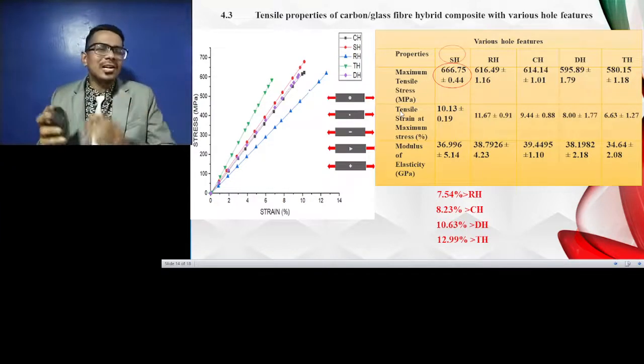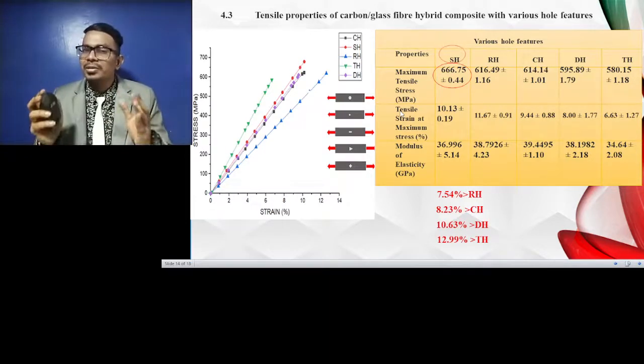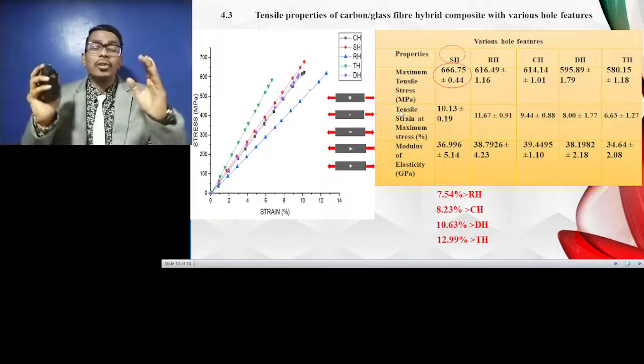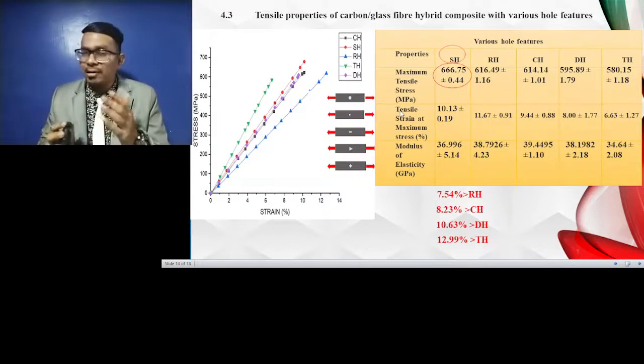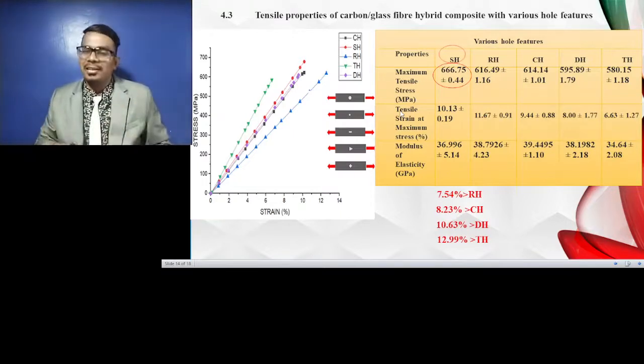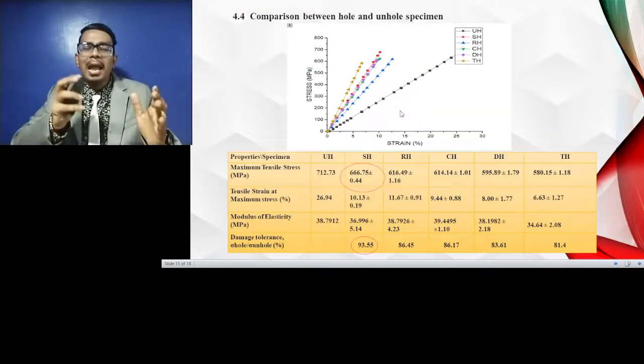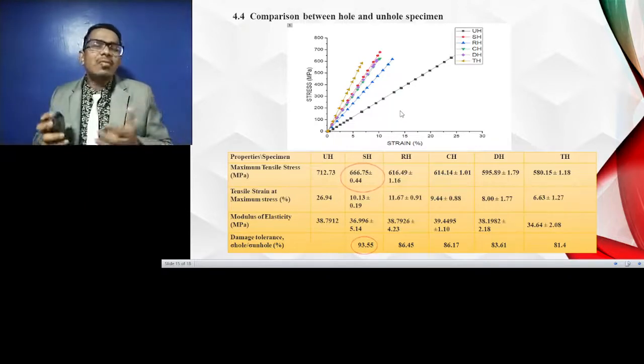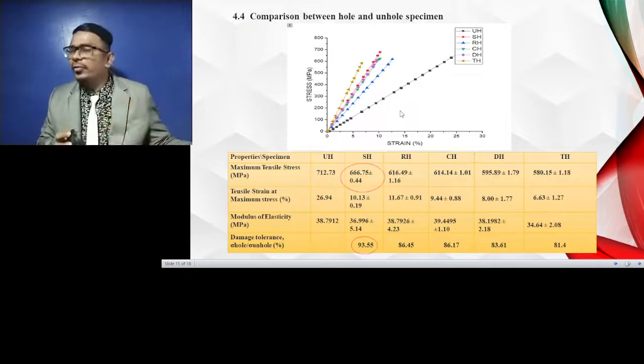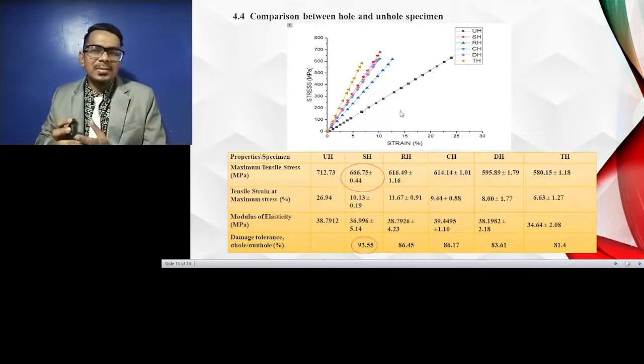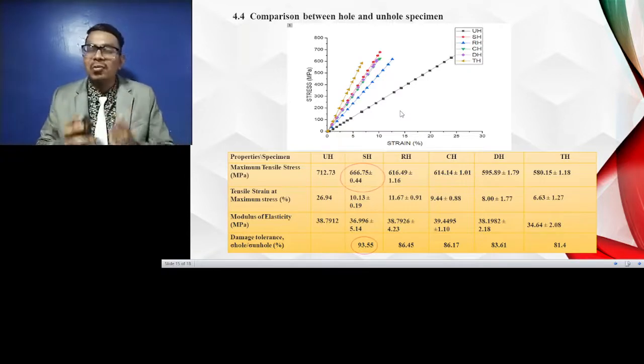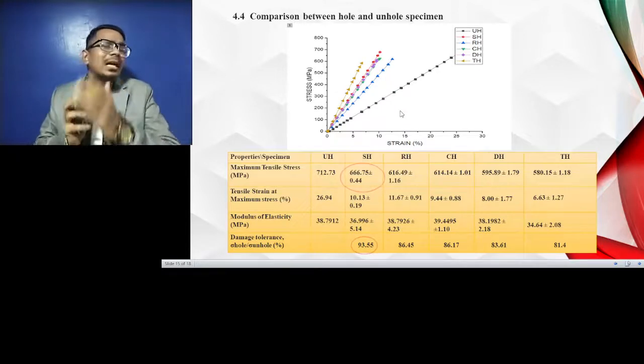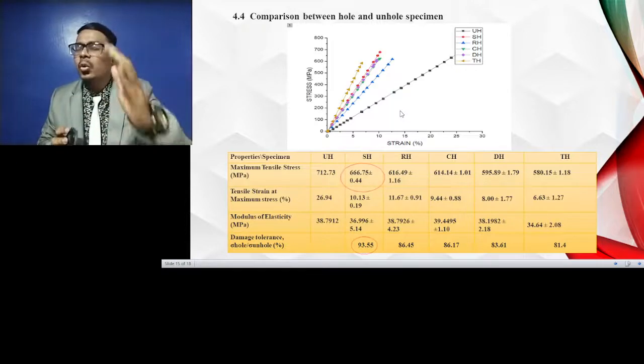In addition, higher tensile strength was recorded by the square hole specimen. The lowest tensile strength was recorded on the triangle hole. Moreover, the recorded modulus of elasticity values show very significant differences despite the use of the same material, same density, and same orientations. Not only this, comparisons between the holed and unholed specimens were also made to further investigate the tensile properties. As shown in the figure, the tensile strength values for the unholed specimens were higher compared to the holed specimens. Based on the data, the maximum tensile strength was recorded in the unholed 90 specimen, while for the holed specimens, the maximum tensile strength and damage tolerance was recorded in the square hole.